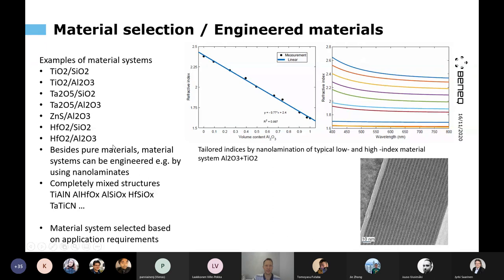Additionally, process conditions such as temperature especially play a role. So at different temperatures, we can get slightly different properties. And then we can also make completely mixed structures. So instead of making 1 nanometer of this and 3 nanometers of that, we can just make one cycle of this and 3 cycles of that. Then you will not see any lines like this anymore. It will just become a mixture. That is another way to generate artificial materials.